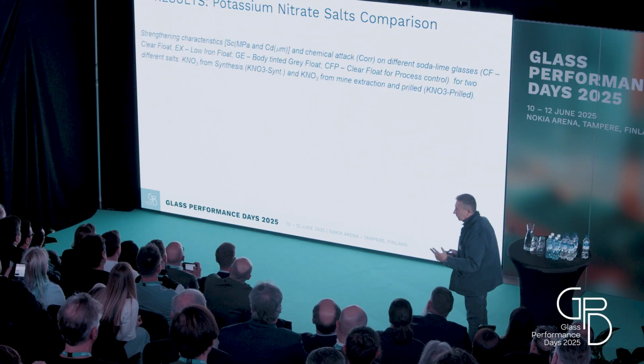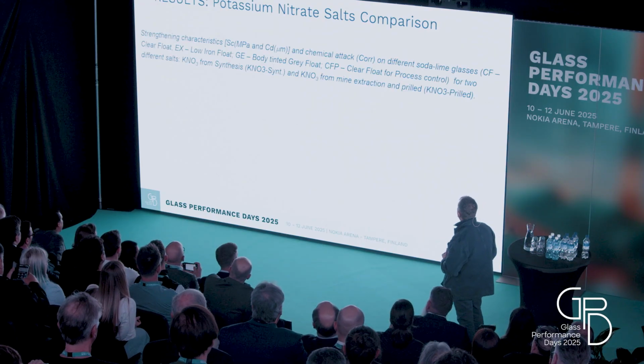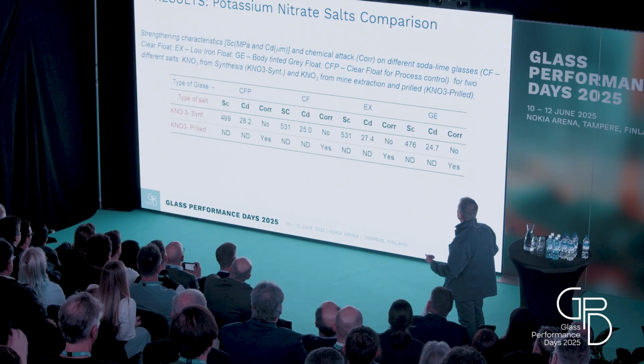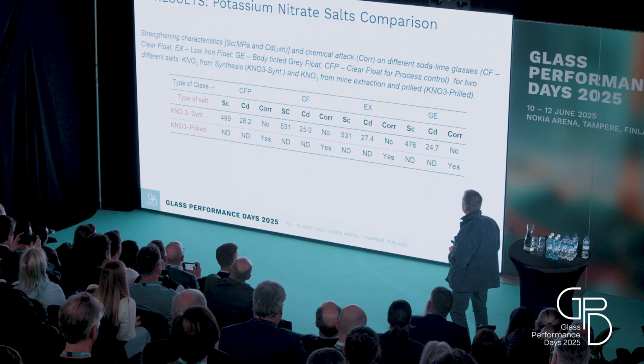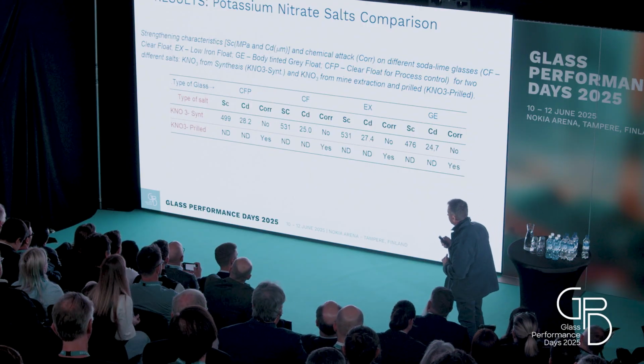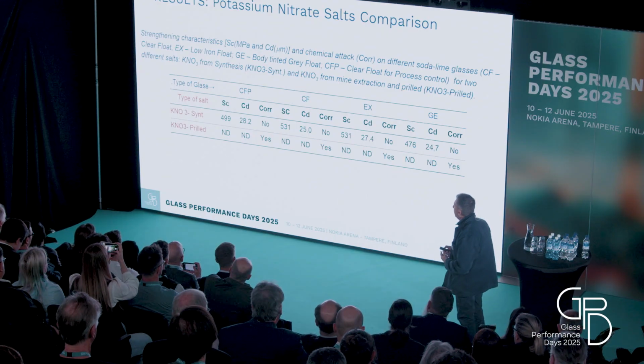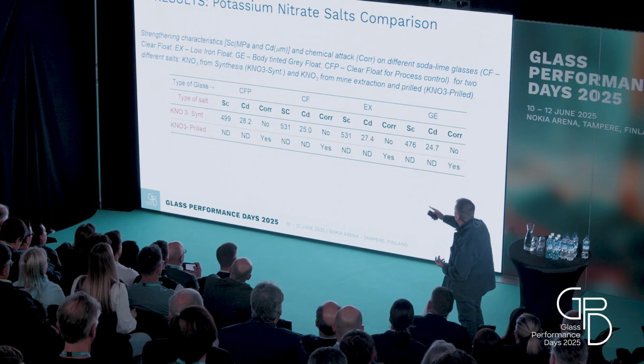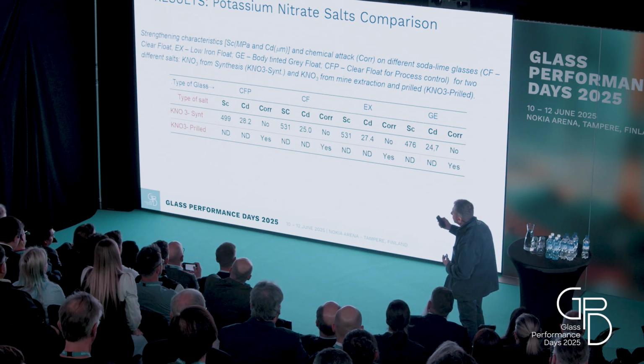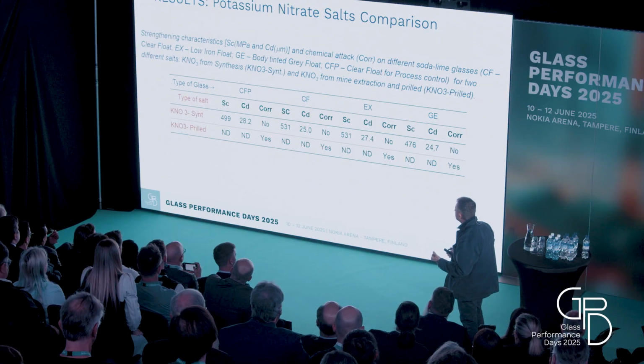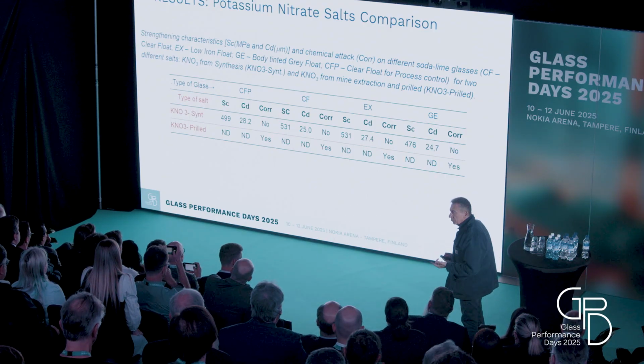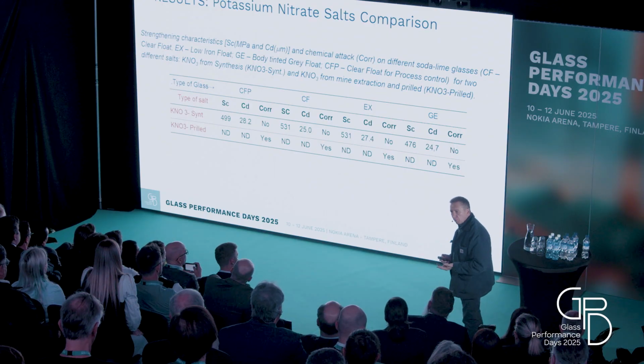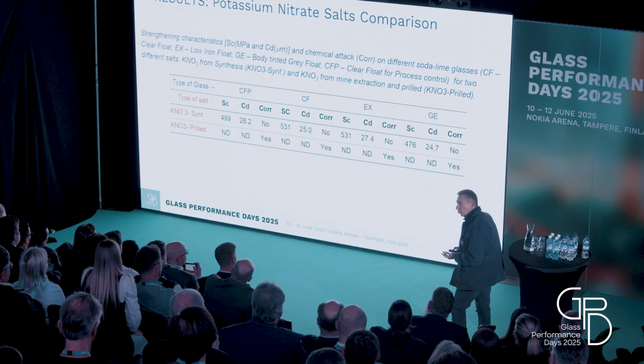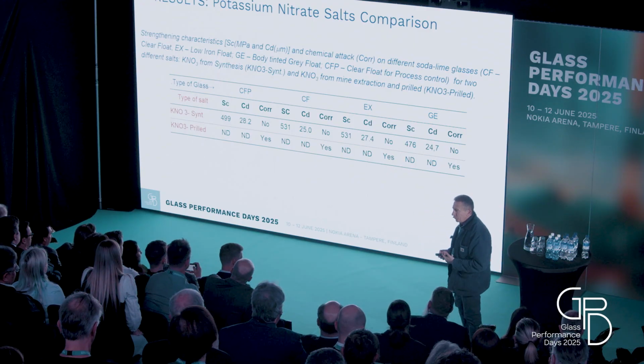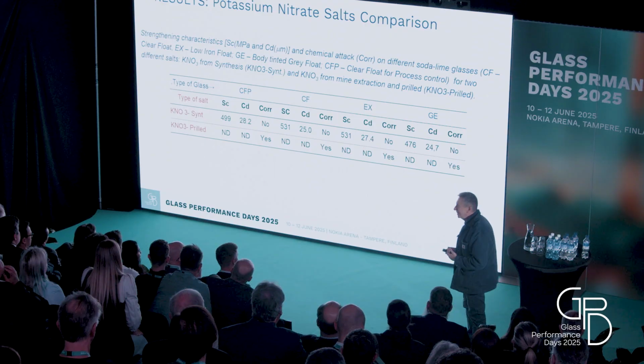Now we made a comparison of two types of salts. One is a salt that has been produced by chemical synthesis. And the other one was an industrial salt made by pellet mine extraction. And those are the values. Basically, the pellet salt doesn't give you any surface compression, any case depth, and also corrodes the glass. That means that this salt is not suitable. Even if it's much cheaper than the other one, I don't recommend using this, unless you have some methods to make it work, if it's possible. And it means not detectable.